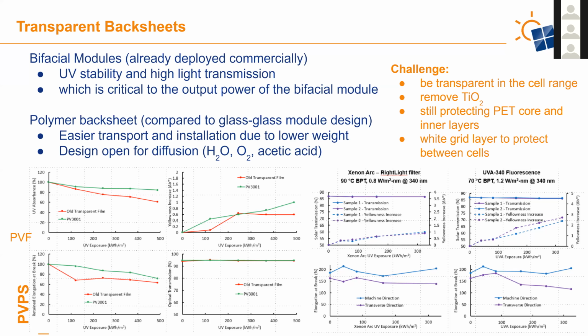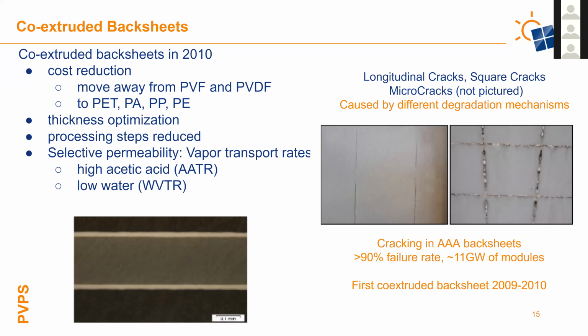As Gernot talked about, polyamide was one of these failures back in 2010, and we moved away from PVF and PVDF to these co-extruded polyamide materials. Co-extrusion helps where we can have much better thickness optimization, reduce the number of processing steps, and be more selective on permeability, so you could permeate high acetic acid out while not necessarily allowing a lot of water into the module.